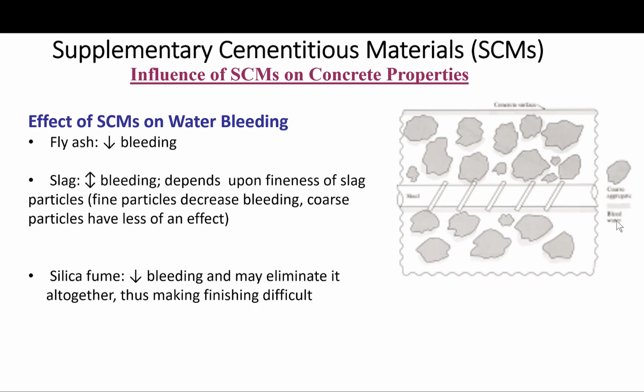As far as the effect on water bleeding, fly ash reduces bleeding. Slag may increase or decrease bleeding depending upon the fineness of the slag particles - fine particles decrease bleeding, and coarse particles have less of an effect. In the case of silica fume, it decreases bleeding and may eliminate it altogether, making finishing difficult. So you have to remember, when adding silica fume, other measures have to be taken to make sure we have good finishability of our concrete.